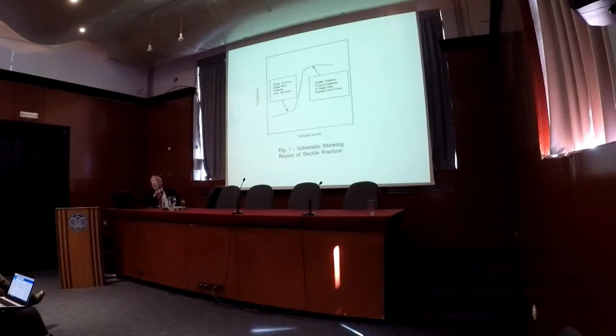Here is some toughness versus temperature. For steel, you can see then typical behavior is like this. At low temperature, you get low toughness. At higher temperature, high toughness. In between, you get a transition.